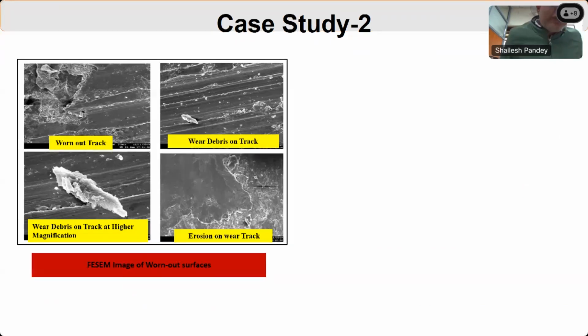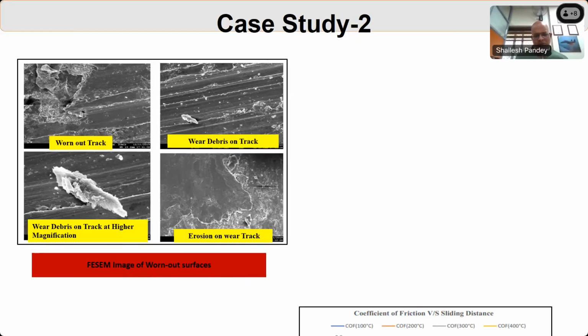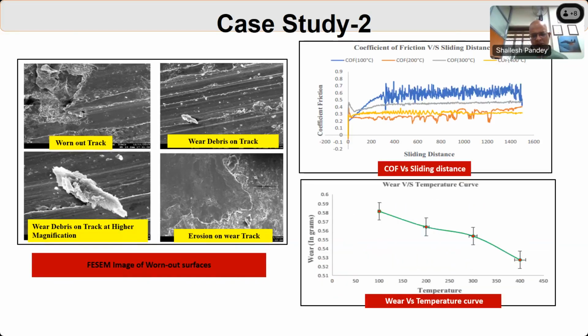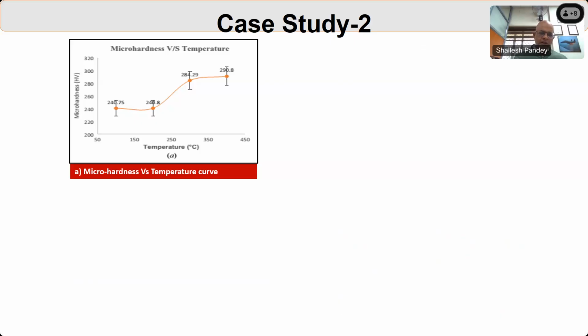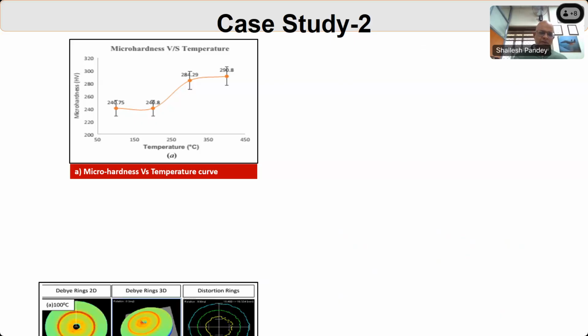Here in this image, you can see the scratch, the abrasive wear, clearly worn out on the surface in the SEM, scanning electron microscope. On the right side, you can see the pin-on-disc image of the wear patterns with the pin-on-disc machine, and the weight loss is decreasing with the increase of temperature, and the microhardness is increasing with the increase of temperature.